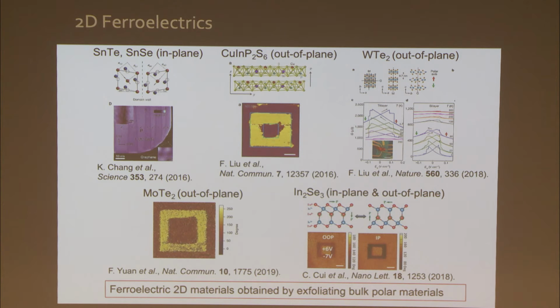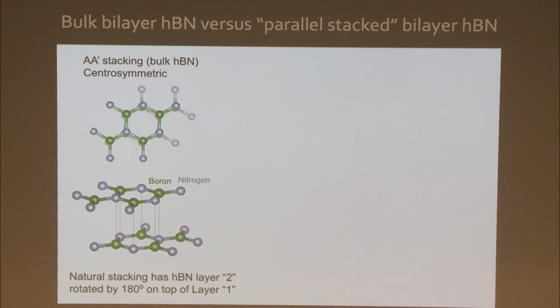Well, I want to show you something completely different. I want to make a ferroelectric out of something which is not ferroelectric, in the same way that I made a superconductor out of 2 things which are not superconducting, okay? But you put them together and you make a superconductor. So for that, I'm going to use bilayer boron nitride, right? I'm going to use hexagonal boron nitride.